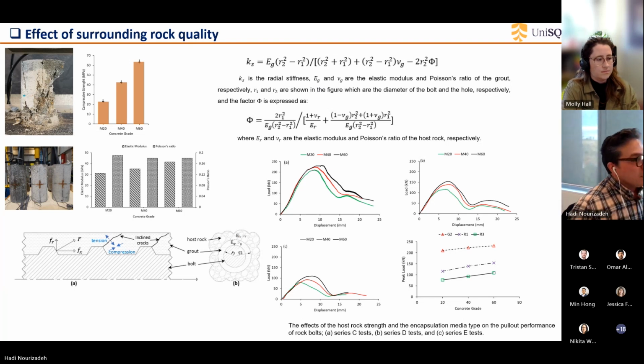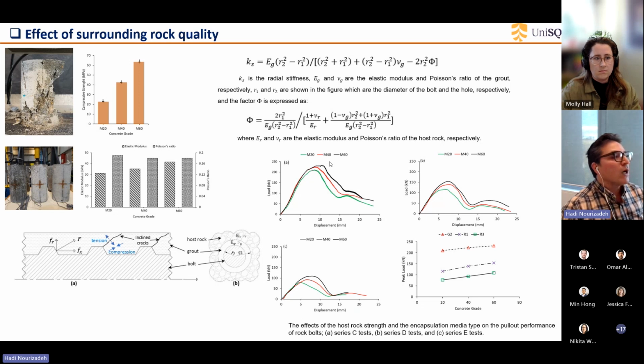As I said, we have main factors affecting the behavior of fully grouted rock bolts, which include the radial stiffness and the compressive strength. In this graph, for example, we have concrete with UCS from 20 MPa all the way to 60 MPa. In the vertical axis, we have the ultimate bond stress, and here we have displacement. Comparing the results shows that higher compressive strength gives higher bond strength as well.